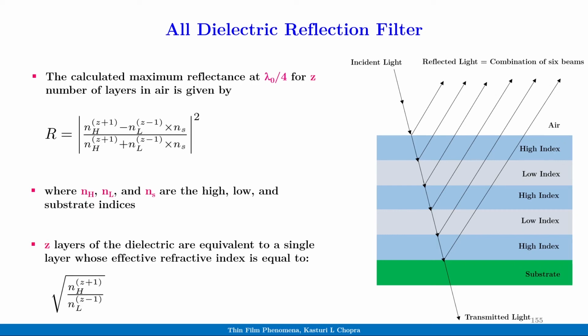Z layers of the dielectric are equivalent to a single layer whose effective refractive index is equal to the square root of NH to the power of Z plus 1 over NL to the power of Z minus 1.